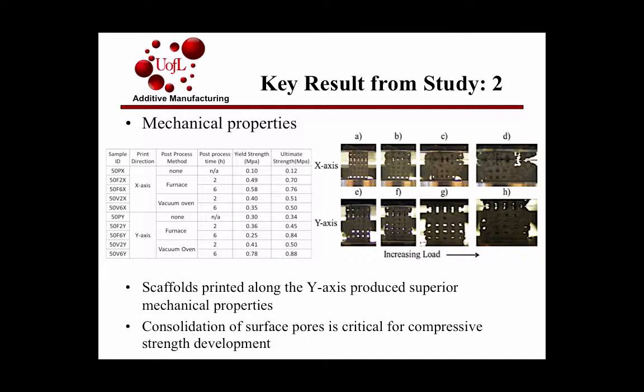So they did a compressive test on 3 samples of each type, and they found that the x-axis parts and the y-axis parts failed in different ways. The x-axis parts had crack propagation along the layers, which resulted in a catastrophic instantaneous failure basically, where it just kind of collapsed. And the y-axis parts showed plastic failure, plastic deformation as the load increased. But they did see that the y-axis printed parts showed superior mechanical properties, higher ultimate and yield strength.